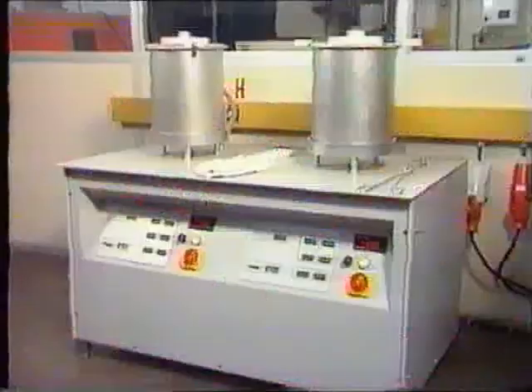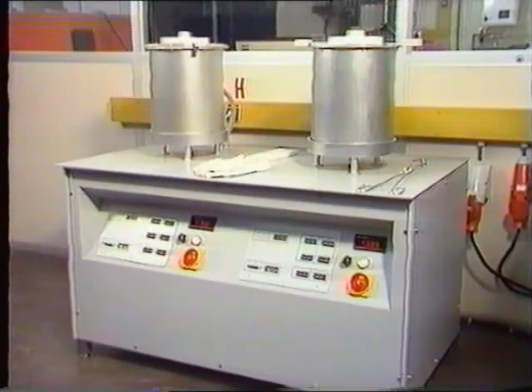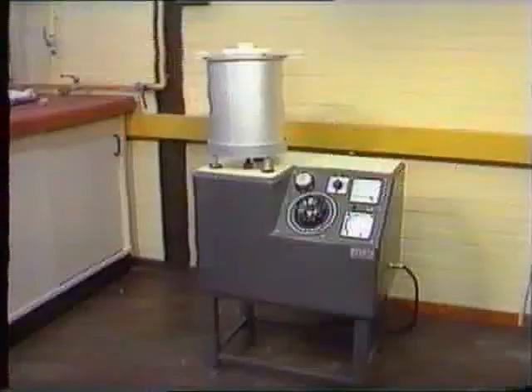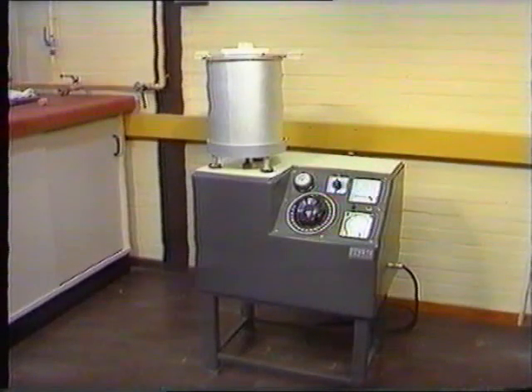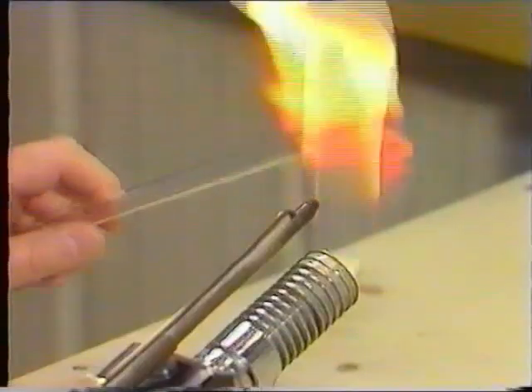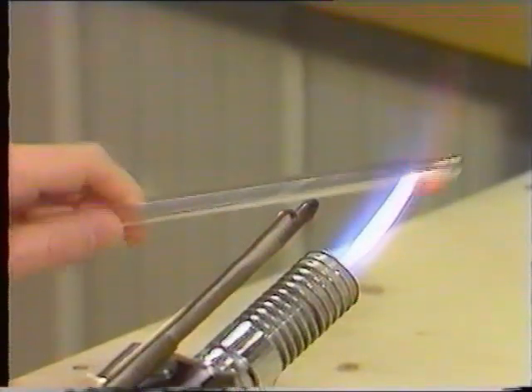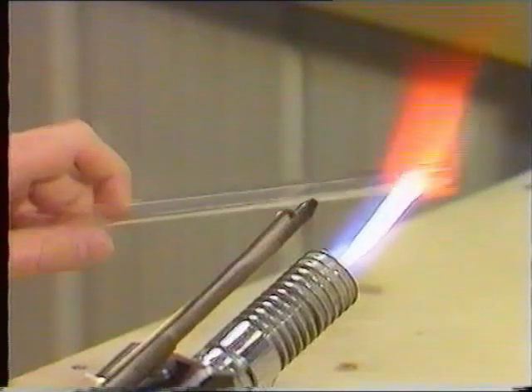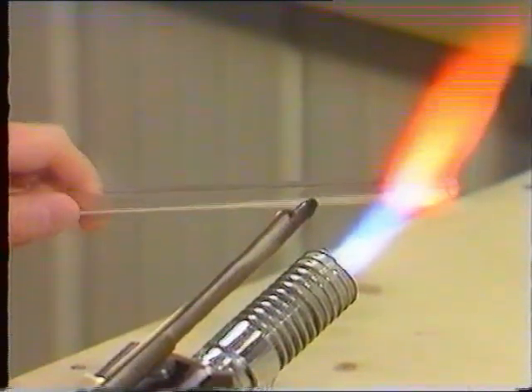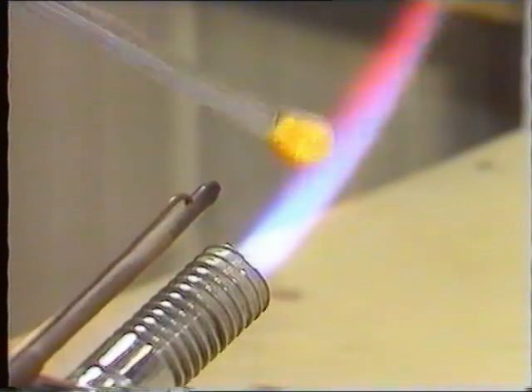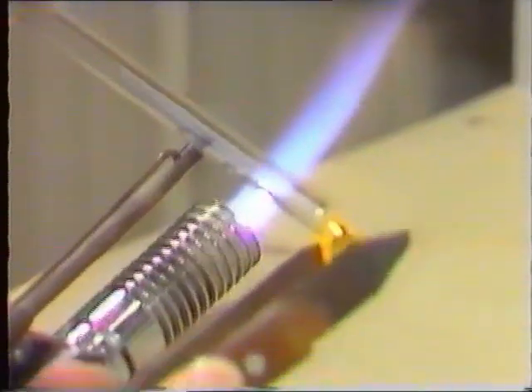Production glass to be tested is melted to the standard glass in a small electric furnace at 30 to 70 degrees centigrade higher, dependent on the glass type. If the production glass is supplied as a thin-walled product, a pair of flat tweezers is used.